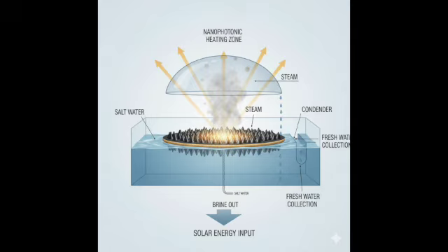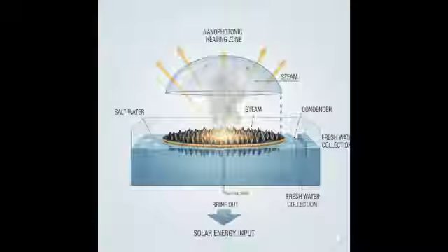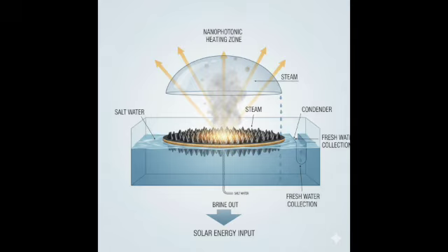Exactly. The density gradient suppresses natural convection, which would normally bring heat from the bottom to the surface where it would be lost. So sunlight penetrates the top layers, gets absorbed by the dark bottom layer, and the heat gets trapped down there. How hot can it get? Temperatures approaching boiling, near 100 degrees C, are possible in the bottom layer. This stored thermal energy can then be extracted to drive a desalination process, like MD, or even generate electricity using special turbines. Is maintaining those salt layers difficult? It requires careful management, yeah. You need to prevent mixing from wind or temperature fluctuations and manage salt diffusion. But it's a way to get large-scale thermal storage.